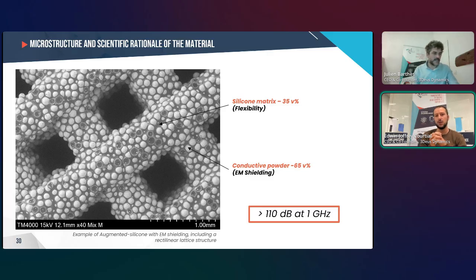It gives rise to an isotropic microstructure where the silicone phase conformally coats the conductive particles while maintaining their connectivity. The result is a three-dimensional percolated network that ensures uniform conductivity and shielding efficiency, reaching more than 110 dB at 1 gigahertz. This microstructural design illustrates how the geometry of the filler directly controls both the manufacturing process and the electromagnetic performance. The next step will be to evaluate whether this performance remains stable across the full frequency range and under mechanical load over time.